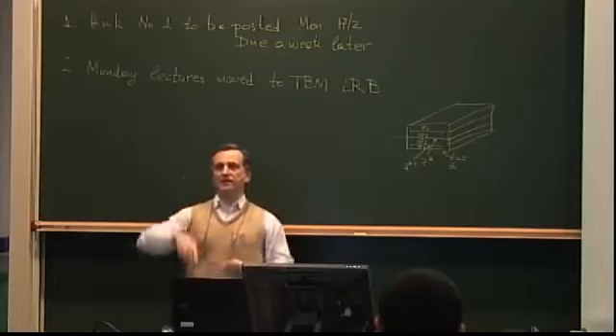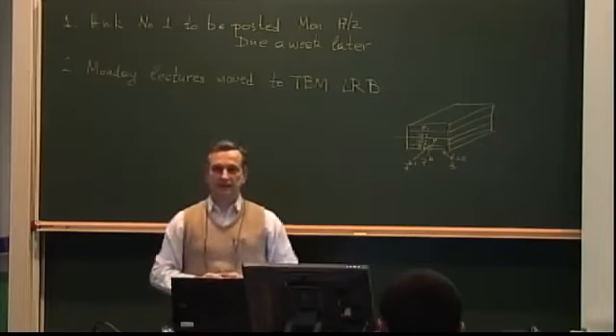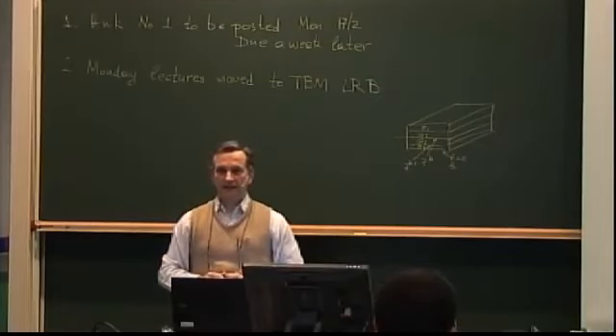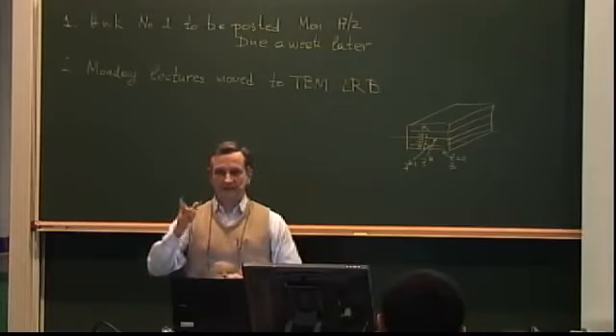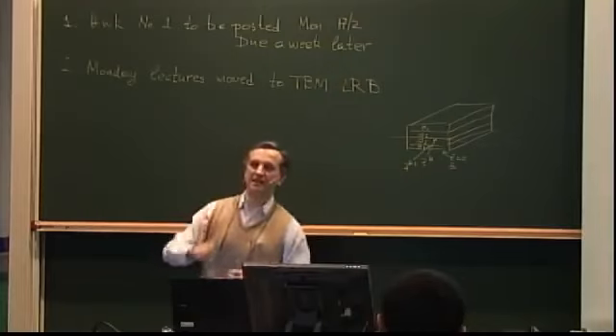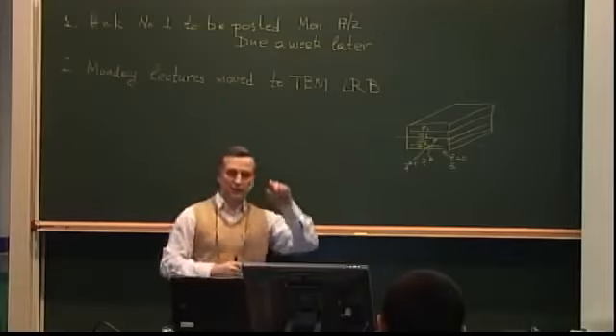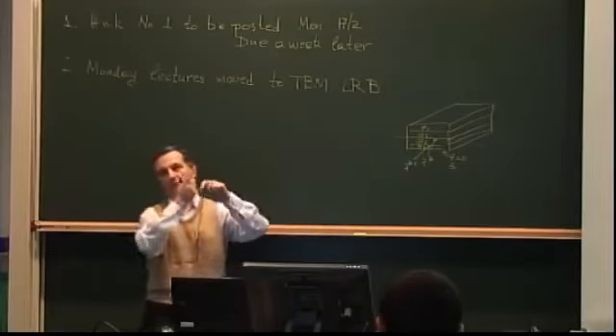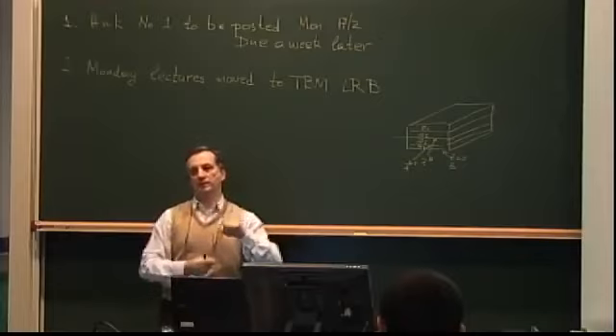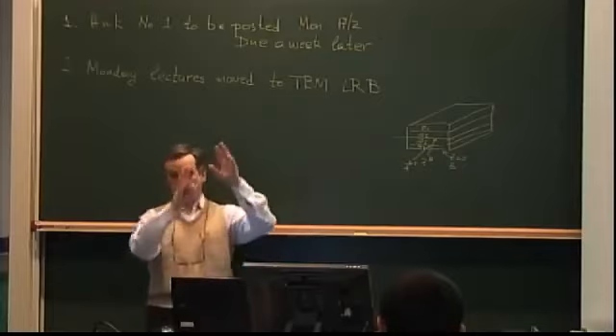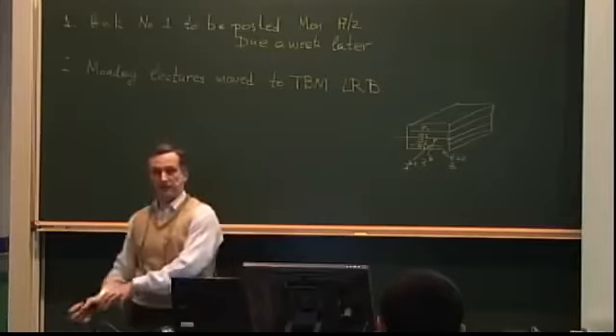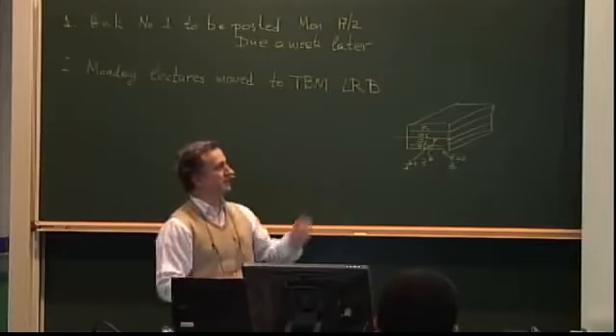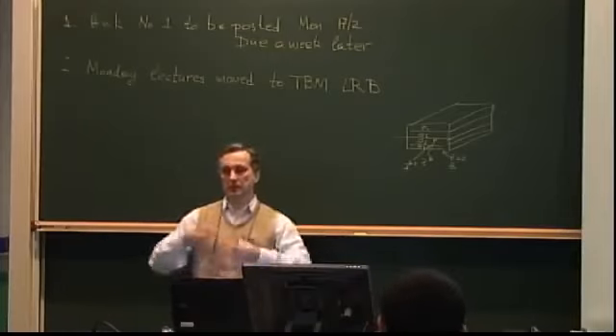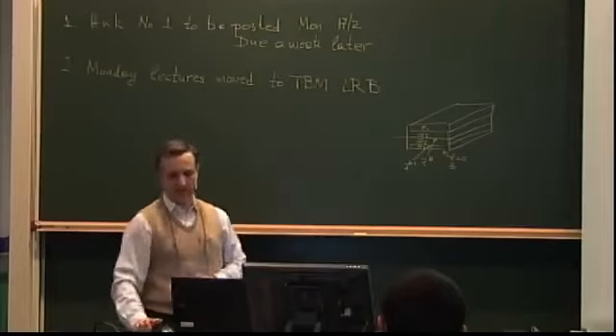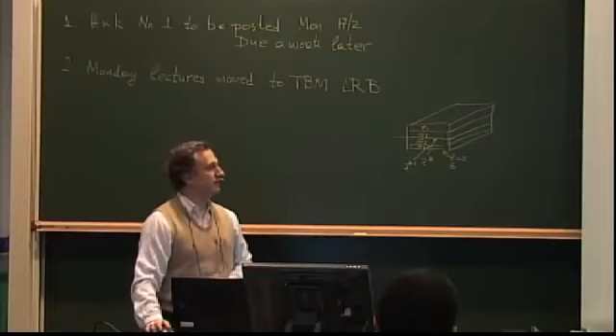There's one more general case, where they are non-symmetric to the midplane. So on top you have plus theta and below minus theta. Excellent. Yes, so anti-symmetric. If at a certain location I have a plus theta and the corresponding location with respect to the midplane I have a minus theta, and that is valid for all the plus thetas and minus thetas, then all the D16 and D26 terms will cancel out because the contributions above and below the midplane cancel. That's very good.